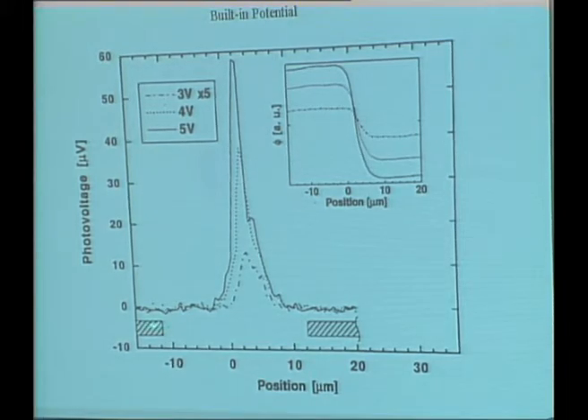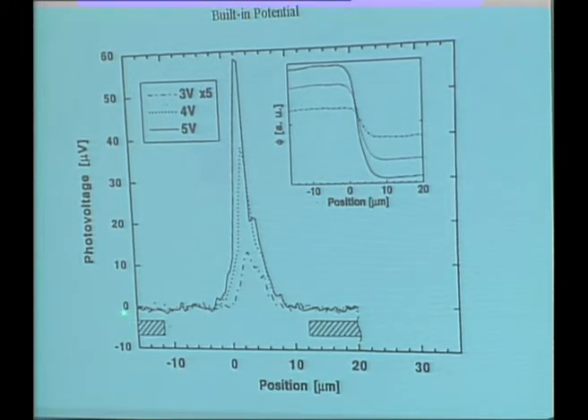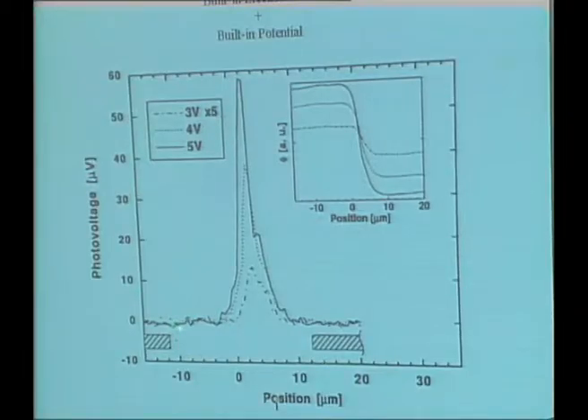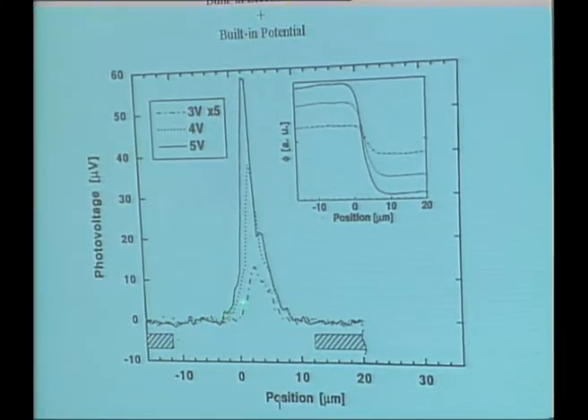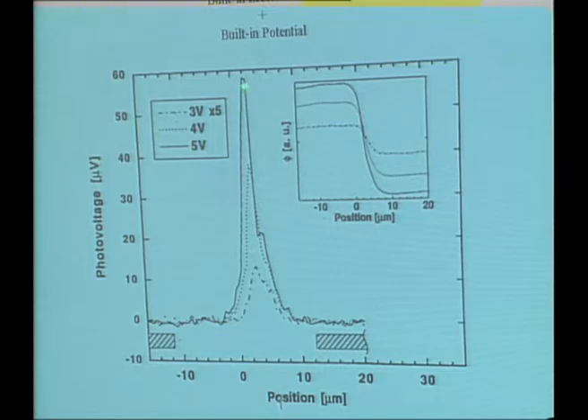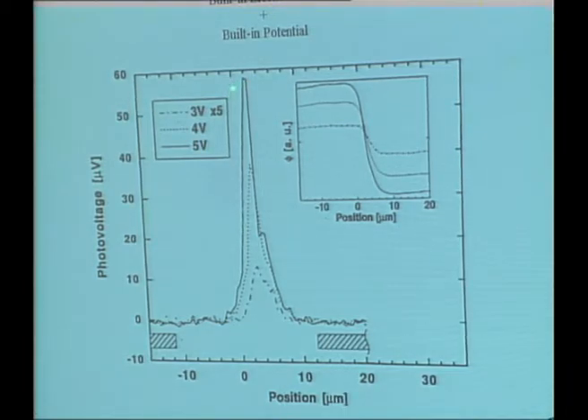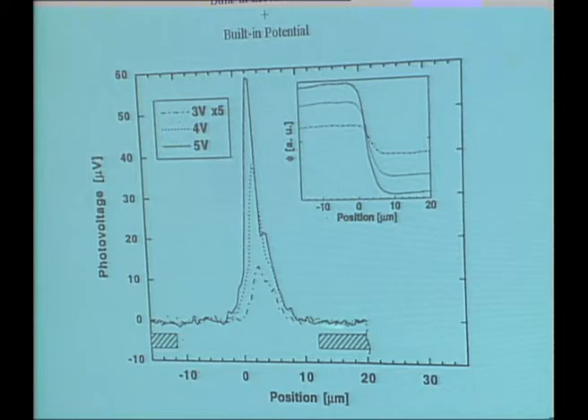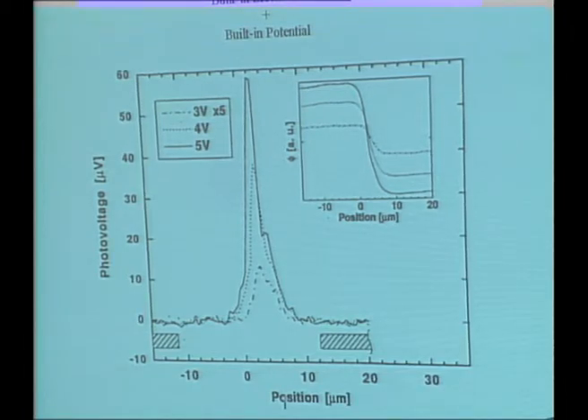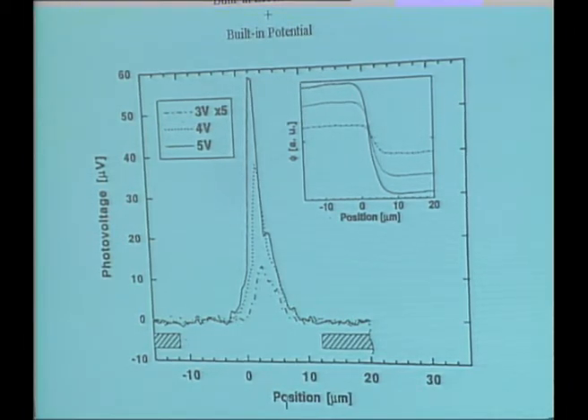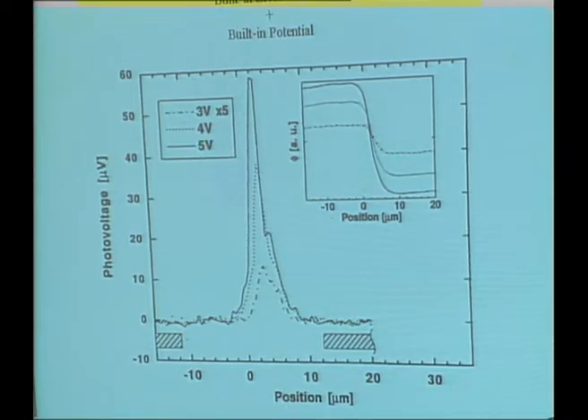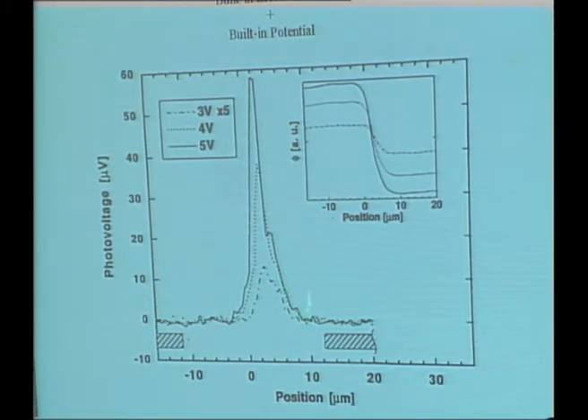And I start on one side, bringing my laser beam along. And the laser beam is focused down to less than a micron, so that I have good resolution. And I don't see any current. And then when I get to this point, current starts to go up, up, up, and I'm going through the I region of the PIN junction, and then I come back, okay? And that was done for 5 volts applied. Here's 4 volts applied. Here's 3 volts applied.